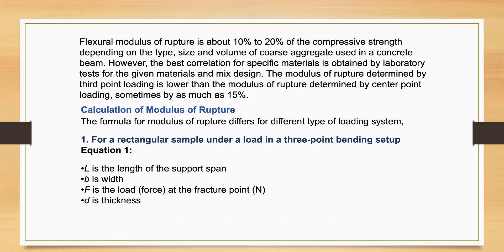The modulus of rupture determined by third point loading is lower than the modulus of rupture determined by center point loading, sometimes by as much as 15%. The calculation of the modulus of rupture: the formula differs for different types of loading systems.